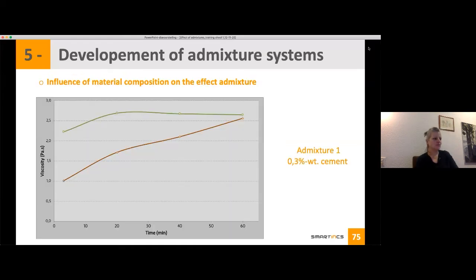And here to illustrate, this is the plastic viscosity that you see in function of the time. A higher value means that you have something more viscous, so you have less workability. Here I made a mistake: the green one should be cement 2, and the brown one should be cement 1, because it starts with a lower viscosity, and in time with the hydration, you see that you have a loss of workability, but this is expected.